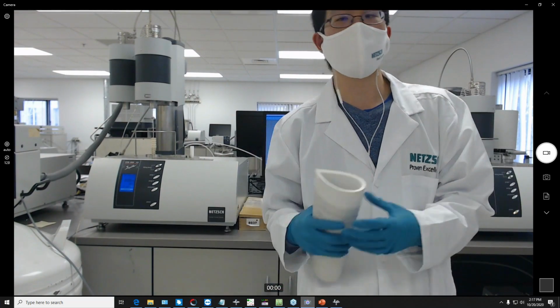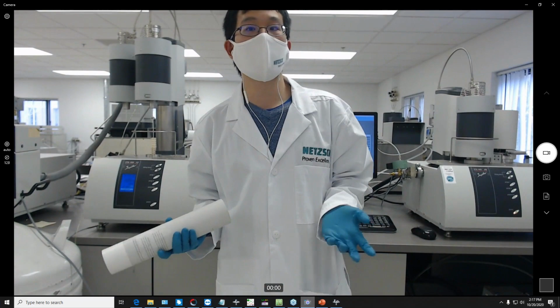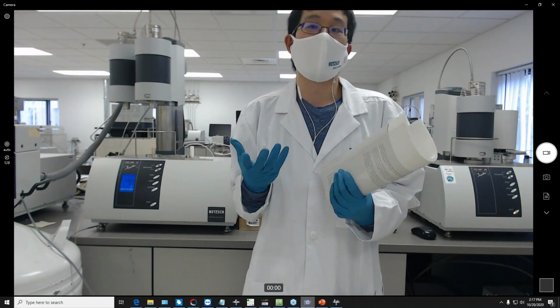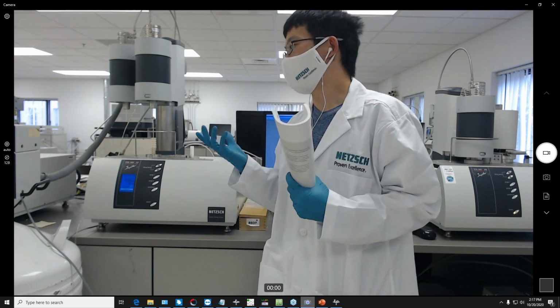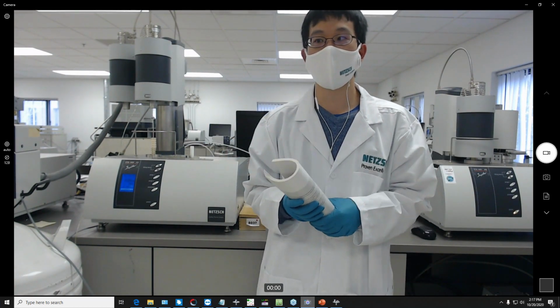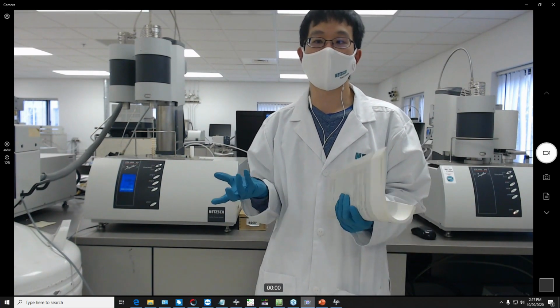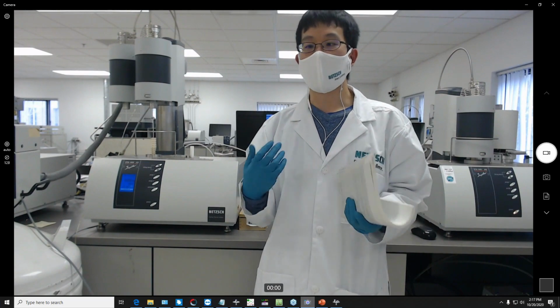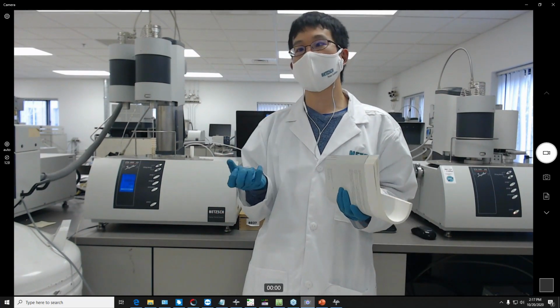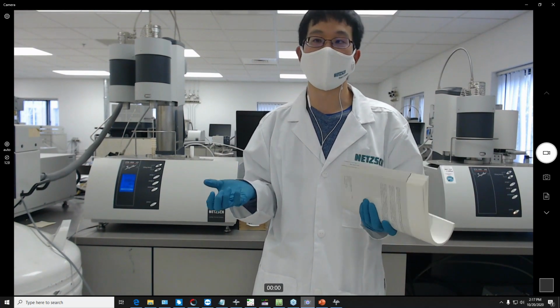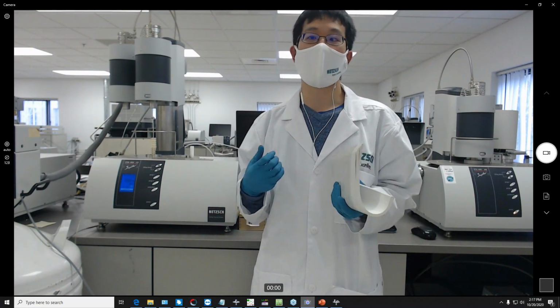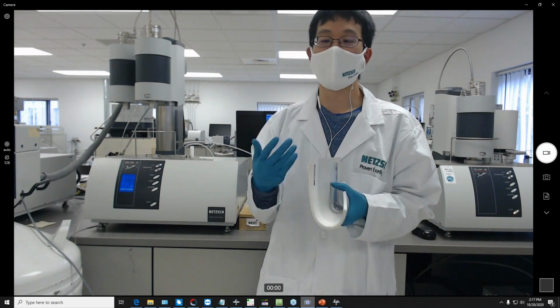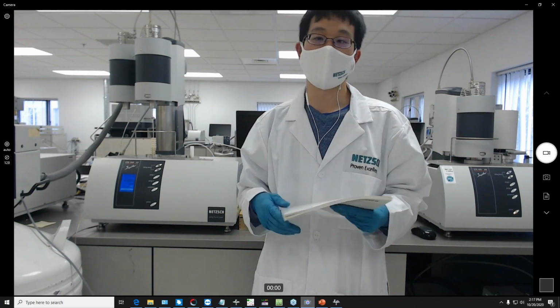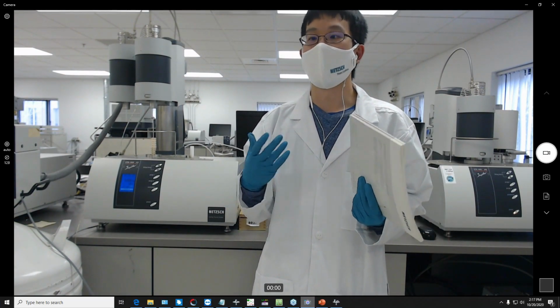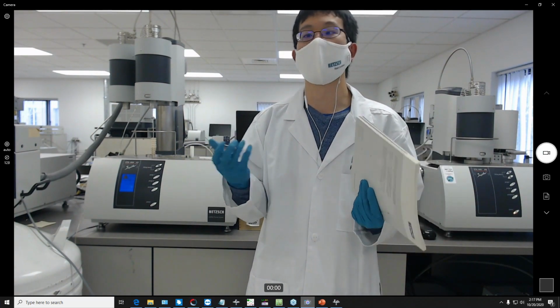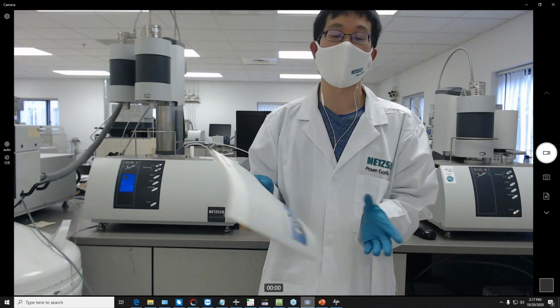In cases where I am dealing with new research samples or unknown samples where I might not know what the possible reactions or interactions are with crucibles and the sample material, I'll start with small quantities such as 1 to 2 milligrams and run it through. Once the measurement is done, I will assess both the crucible and the material to see if any interactions occurred. If none occurred, then I can increase the sample quantity, and after each iteration, I'll reassess. Sometimes it might not occur in small quantities, but with larger quantities you might have a different sort of kinetics and reaction that could also impact your measurement.